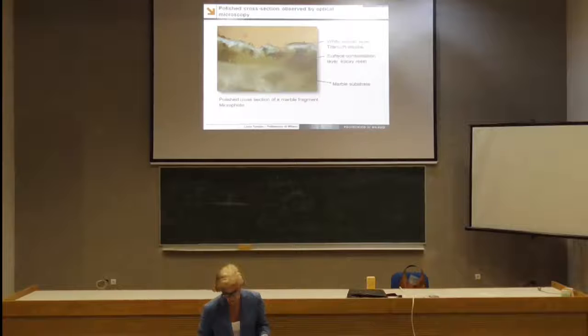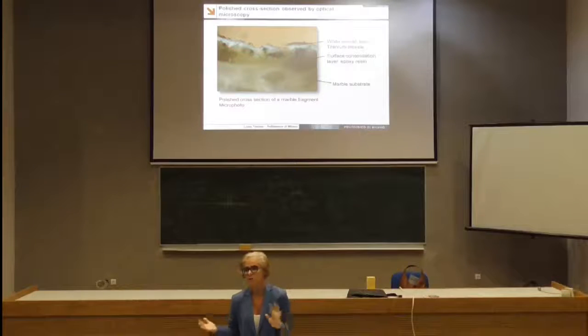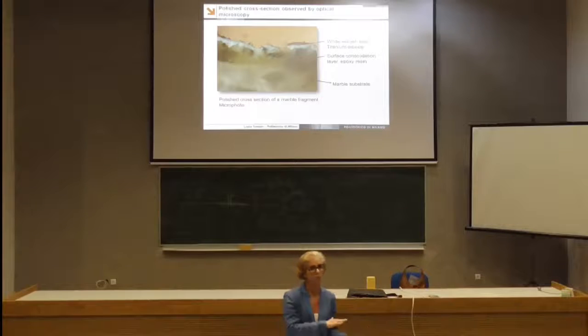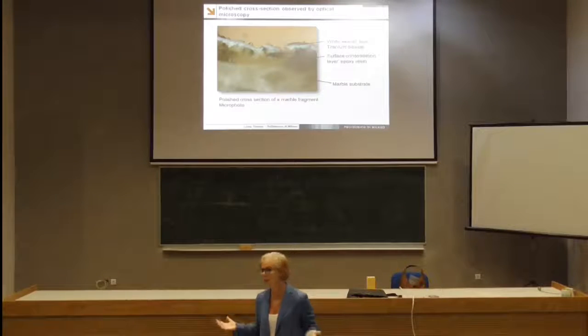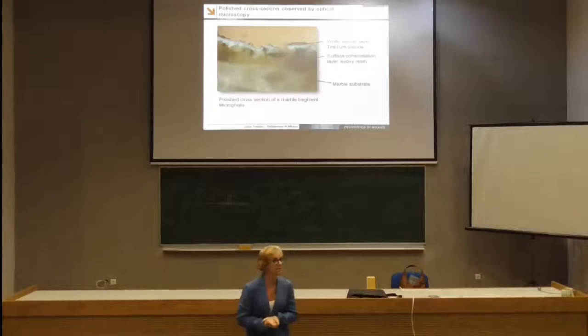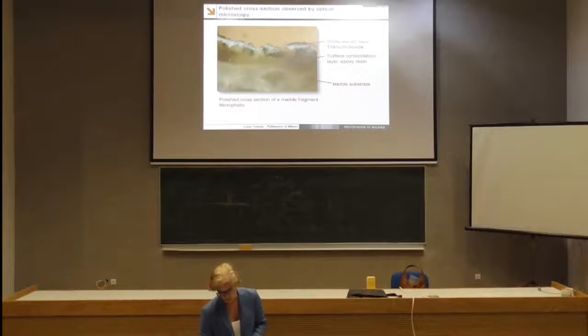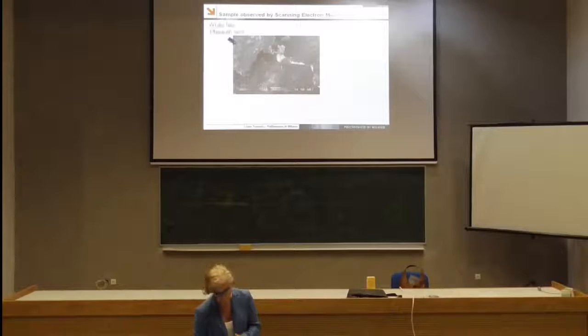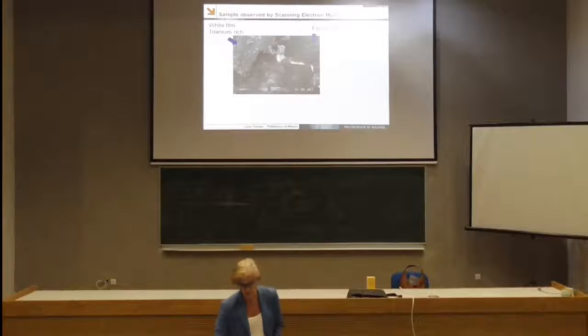This is this famous cross-section with the white varnish, with titanium dioxide as white pigment, because the surface of this church was either black or yellow, no more white as the marble was expected to be. So also in this case, what we could assess during the study of the deterioration process was that, for instance,